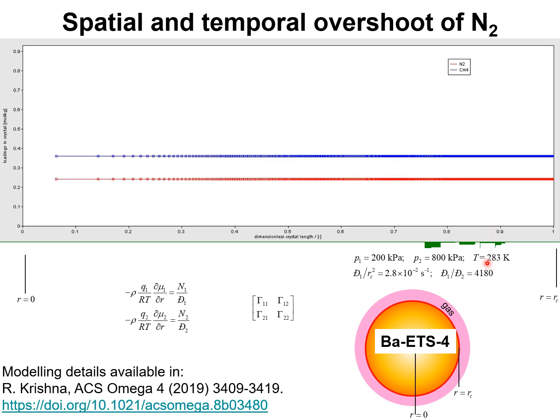The essential aspect of kinetic separations is that the transient uptake process is terminated after a time interval during which the component loadings within the particle exceed the values that are in equilibrium with the bulk gas mixture. In other words, the attainment of supra-equilibrium loadings of nitrogen is an essential feature of kinetic separations.